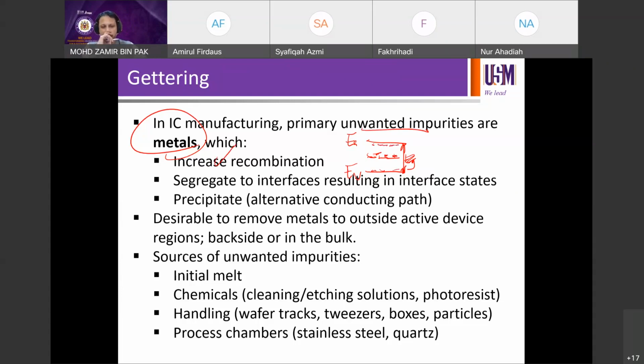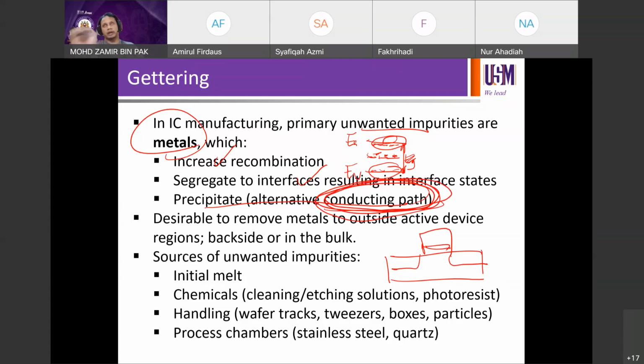The unwanted impurities are metals which also segregate to interfaces, resulting in interface states. So these are all interface states, right? They will suck in and trap the carriers, and you end up with fewer carriers in the devices. Precipitation also provides a conductive path. Later on, we're going to see that when you make a MOSFET, you want certain regions of your wafer to be conductive and some other regions to be insulating in nature. If you have metal somewhere, for example in the insulator part, it will provide an alternative conducting path, because metal is conductive and you don't want that area to be conductive. But due to metal, that area becomes conductive accidentally, which we cannot control. So that's why you have to really control the precipitation by performing the gettering process.